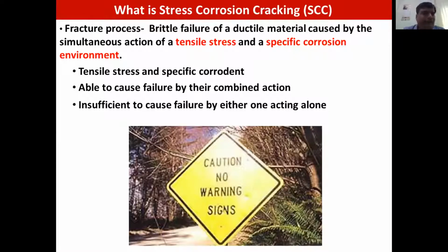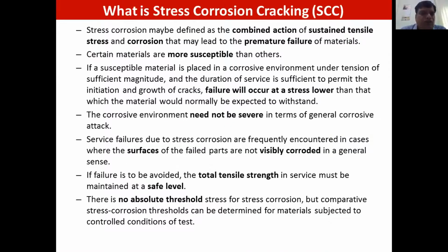When you look at the stress corrosion cracking literature, you can note that tensile stress and a specific corrodent are the most important. You should always have a tensile stress component. For example, aluminum alloys in chloride environment, stainless steels in chloride environment, brasses in ammonia environment. So there is a list of combinations of materials and media that are not compatible. This is how the D5 launch was aborted, and subsequently we used a 2219 aluminum alloy propellant tank and flew the same launch vehicle successfully, except for the propellant tank. And of course, this is the know-how about stress corrosion cracking.